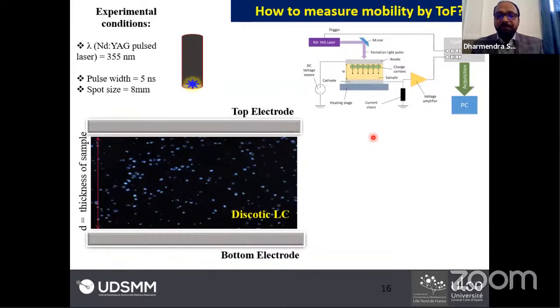It is a very simple setup. It consists of a pulse laser. We use Nd:YAG here, and we can tune the radiation wavelength, but we use 355 nanometer. And these are some other specifications. So what happens when we irradiate any material with the laser light? Because these liquid crystals are semiconducting in nature, they produce excitons. An exciton is a bound state of electron and hole, but it is not stable. So they get separated due to thermal dissociation.